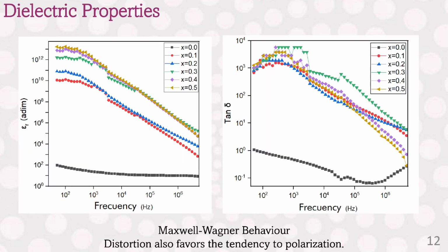The figure shows the relative permittivity values as a function of frequency. It is observed that for low frequencies, below 100 Hz, there is a maximum permittivity that begins to decrease as the frequency increases for the doped samples. However, in the undoped sample this does not happen. This is attributed to Maxwell-Wagner behavior, which tells us that large contributions, especially at low frequencies, may be due to charge accumulators that could be defects such as grain boundary vacancies or porosity, which contribute to the dielectric loss or increase in conductivity. Dielectric losses are shown, which are observed to increase in the doped samples with respect to the undoped one.